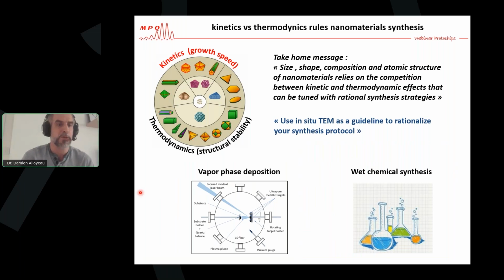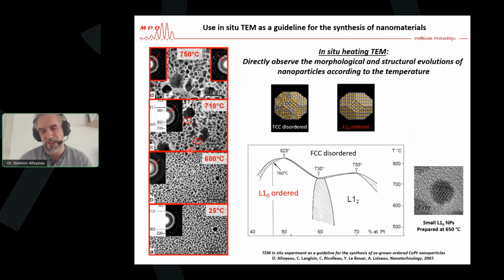So what I mean by kinetic effect is usually the growth speed, and what I mean by thermodynamic effect is the structural stability of your material in its given environment. And I want to show you that you can really use in-situ TEM to better understand this competition between kinetic and thermodynamic effects. And actually, it's a very old idea in my group, because I want to show you, as an introduction, a very old experiment that I did during my PhD, almost 20 years ago.